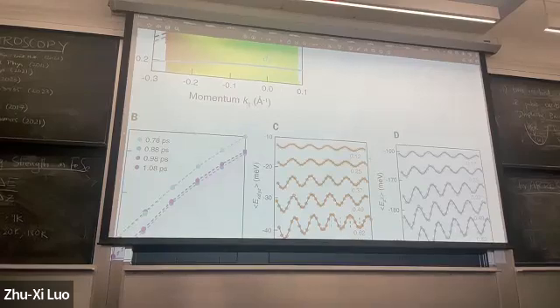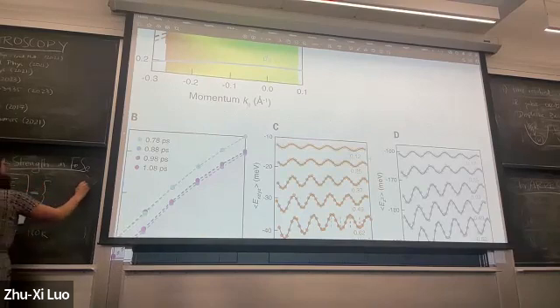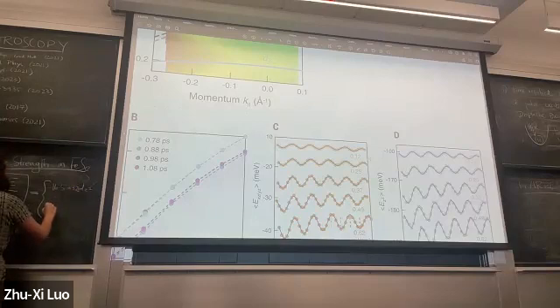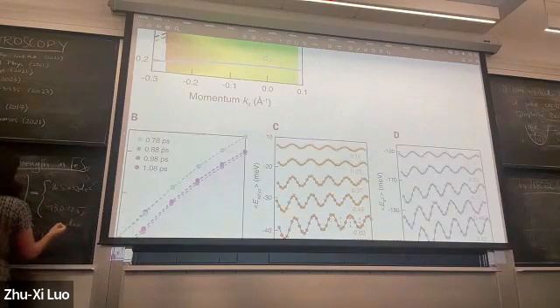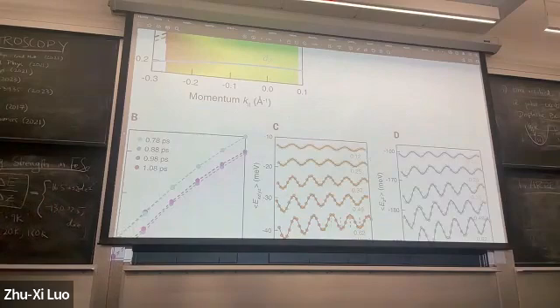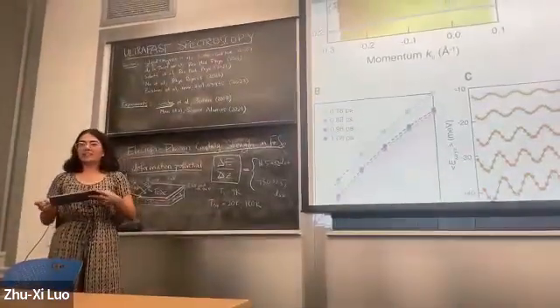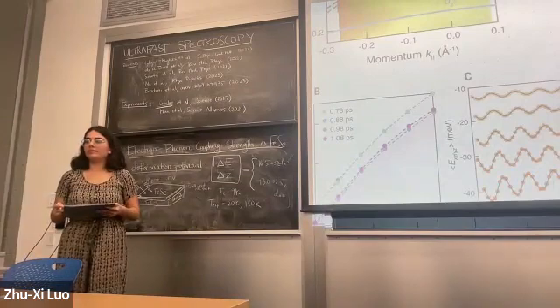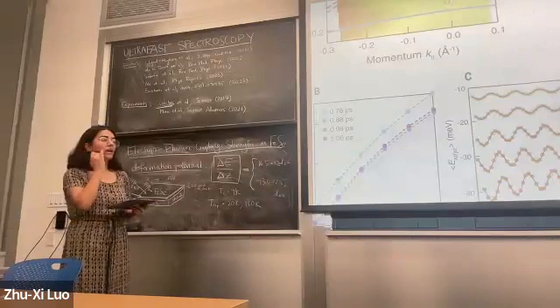Did they quantify the strength of the electron phonon coupling? Yeah, exactly by this formula, where this is the amplitude of the band oscillations. They found for one band it was minus 16.5, and for the other, minus 13, for the XC band. And just to compare, the DFT estimates were minus 1.6 and minus 8.5 or something. So pretty drastic underestimations of how strongly the phonons and the electrons couple. Those are just the variation of the band energy over the amplitude of the oscillation.